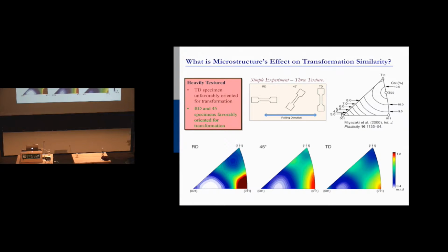To start off, we said, okay, using that theory, how good are these different specimens that we've cut out going to be? So we took XRD data on them. So this is our RD, 45, and TD. Looking at this, you can see here, this is the transformation strain. That's basically how long the plateau is. So the longer the plateau is, the better, the more strain you can get, the more bendy the material is. That's the way to think about it. Okay? You get more bang for your buck from the transformation. And if you have texture here or texture here, you have very large transformations.